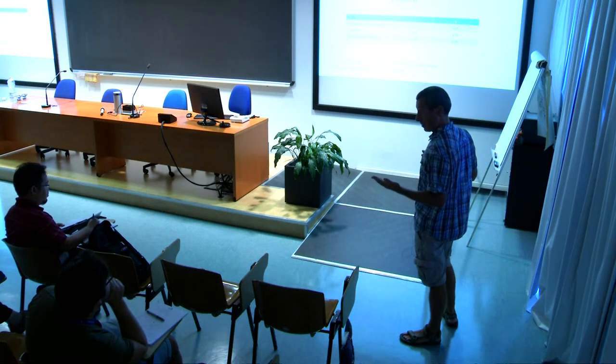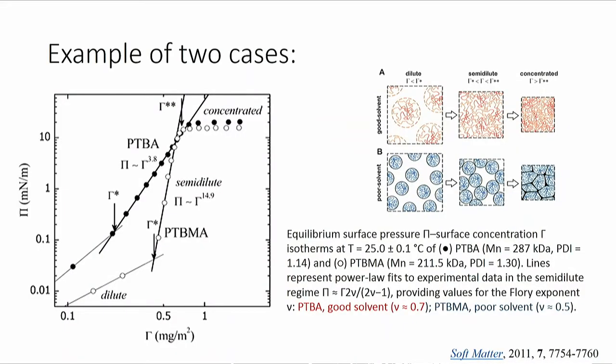And this same thing happens on the surface. Depending on the behavior of the polymer on the surface, you can have a good solvent situation in which the polymer really spreads out and likes to spread out. Or in the poor solvent regime, you have patches that are kind of rigid and avoiding each other. And in either case, you have a different dependence of the surface pressure on the area. So just by measuring the Langmuir isotherm, that is the surface pressure as a function of the area, and seeing how this changes, you can tell which kind of situation you have. These are two different polymers, poly-tert-butyl acrylate and poly-tert-butyl methacrylate. This one is in a good solvent, so it's a very shallow dependence. PTBMA is in a poor solvent condition, so it has much